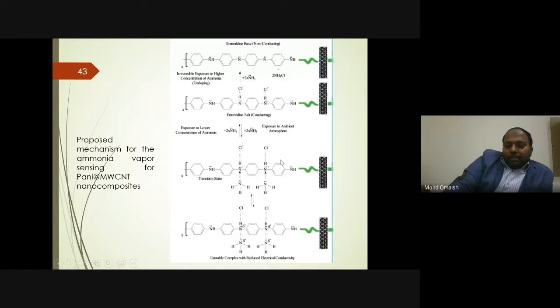Here we propose that during exposure, the ammonia interacts with the amine nitrogen and forms an unstable complex, and this restricts the movement of charge carriers, which drops the conductivity. But under ambient conditions, the ammonia goes away and the conductivity is restored. During long exposure, there is electrical compensation, that is neutralization, and that will also decrease the conductivity.